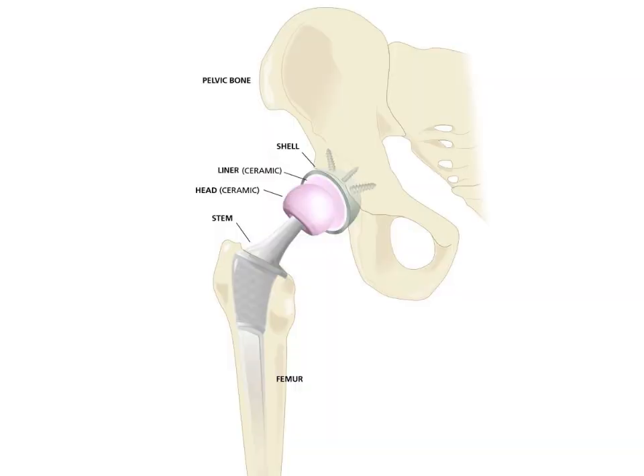Another thing that is made with silicon nitride are medical-grade implants. This involves mixing the silicon nitride powder into a slurry that is then used to form the desired shape. The most popular method of doing this is using laser-induced slip casting, which is an additive manufacturing technique that combines the principles of slip casting with a laser to build objects layer by layer. The object is created as a green body part, but it is still extremely fragile in this state. It is then placed in a high-temperature furnace to go through the process of debinding and sintering. This process removes binding aggregates and solidifies the silicon nitride, making it extremely rigid and strong.